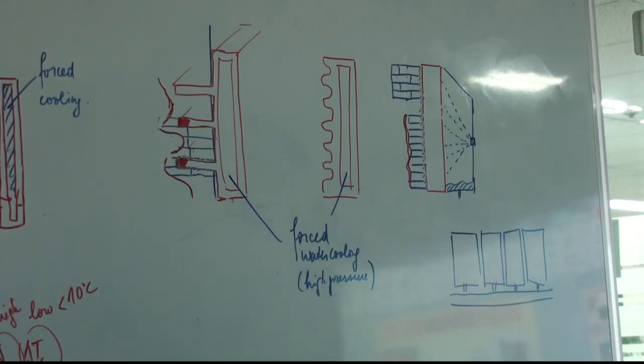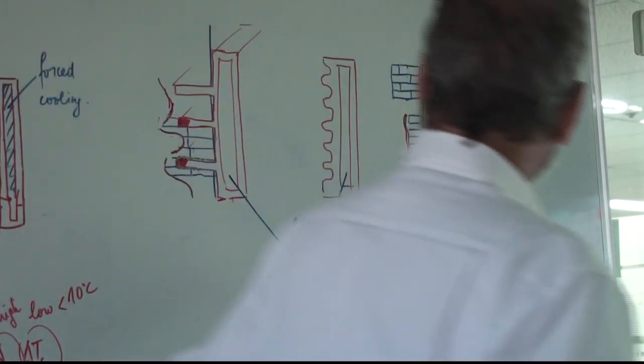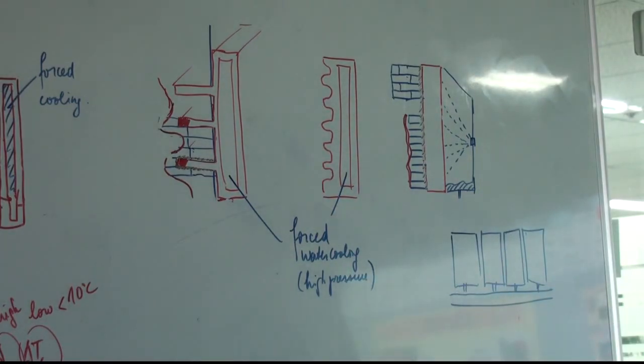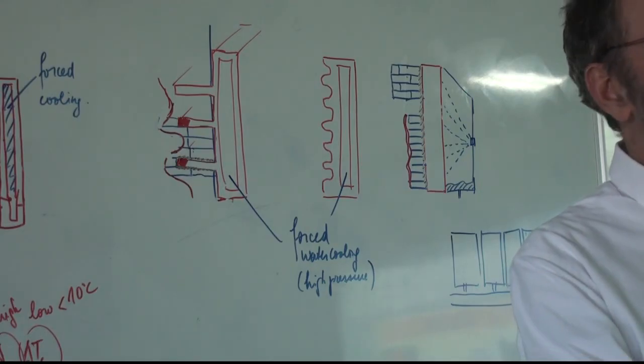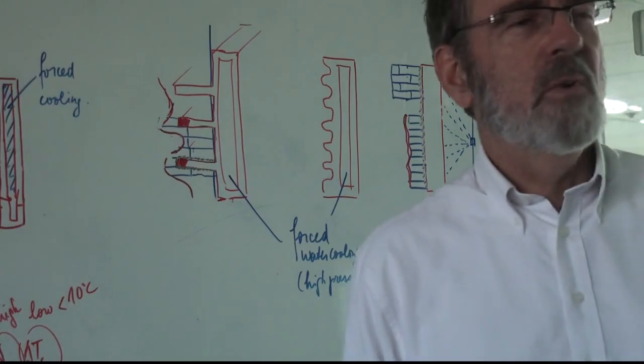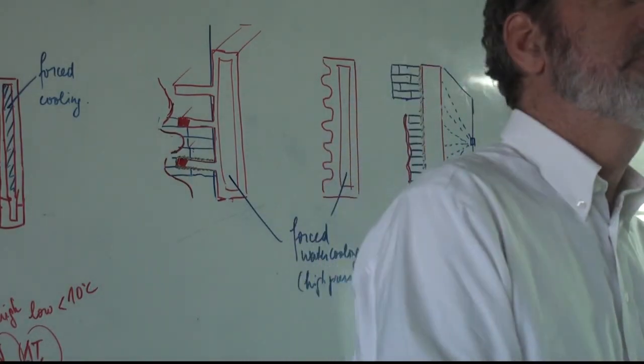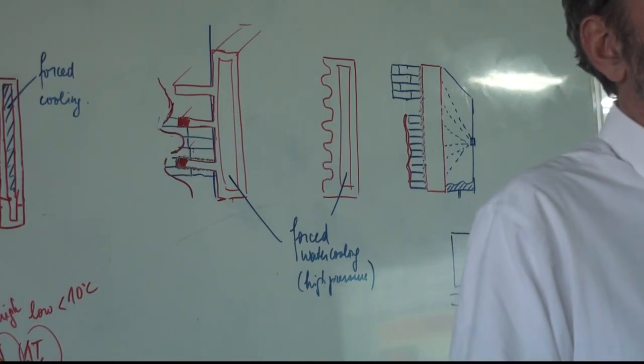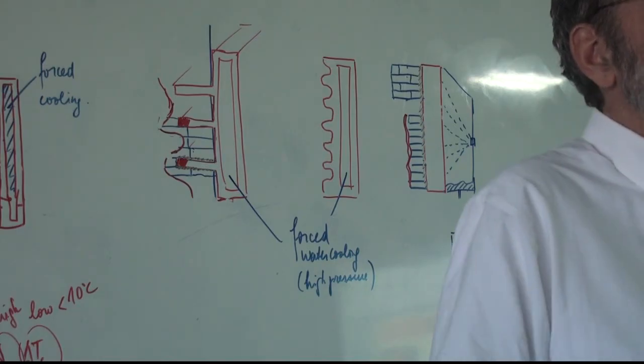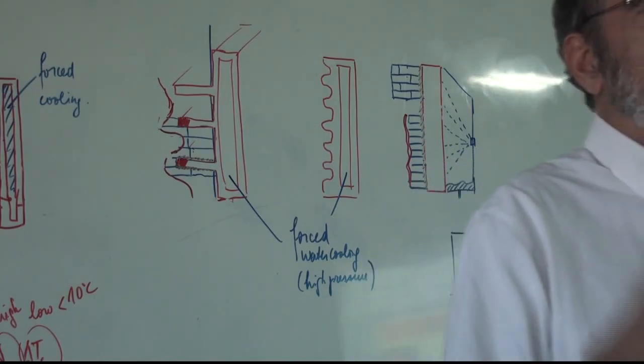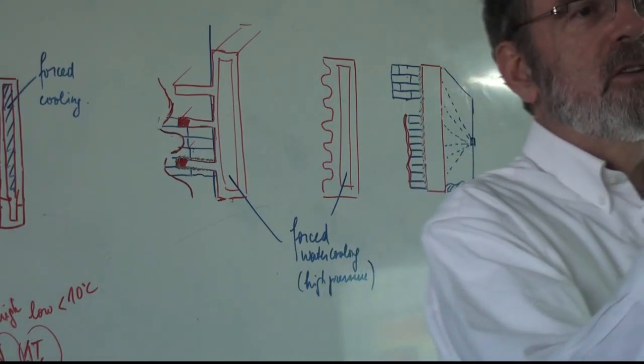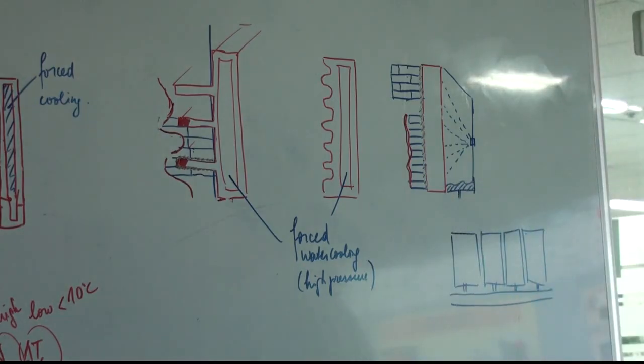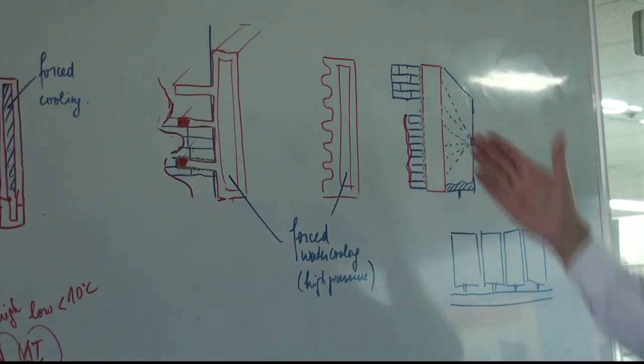You cannot measure this because when you empty the furnace, since the temperature has decreased, you have a very thick layer. But it's not in reality. In reality, you can calculate it. It's a layer of probably less than 1 centimeter, a few millimeters, probably, when you have an established situation. Because when you cool the furnace down and you empty it, everything is freezing, and then you obtain a thick layer. But that's not true. In established situation, before stopping the furnace, you have a very, very thin layer. But it's enough. It stabilizes the wear of the refractory.